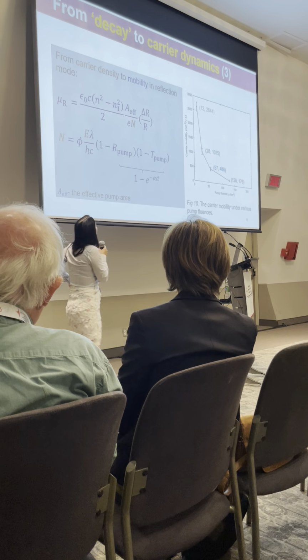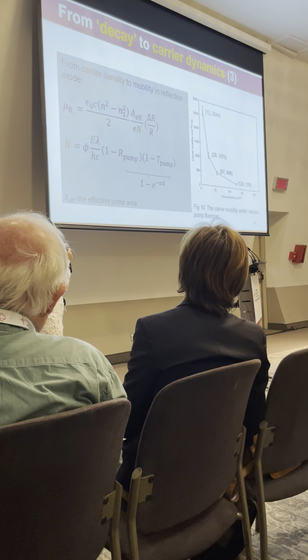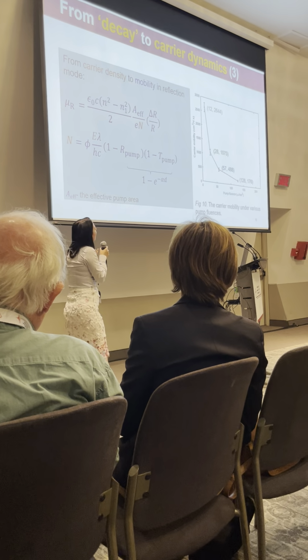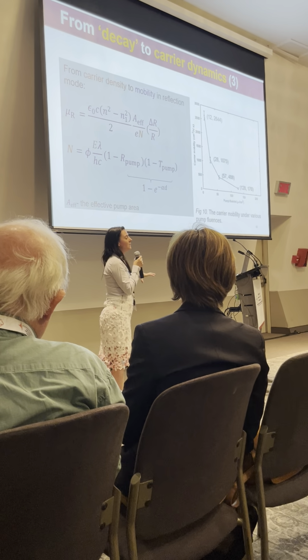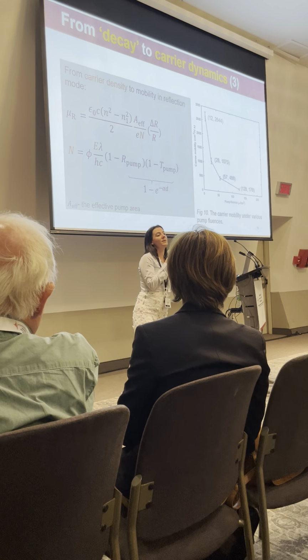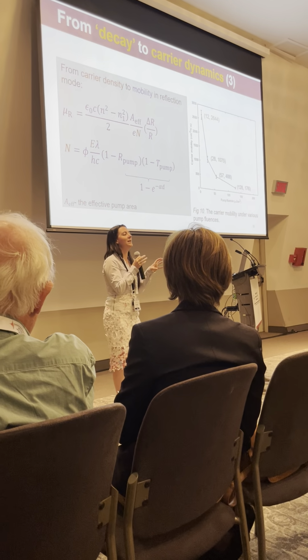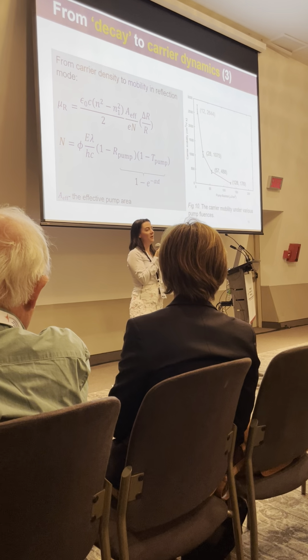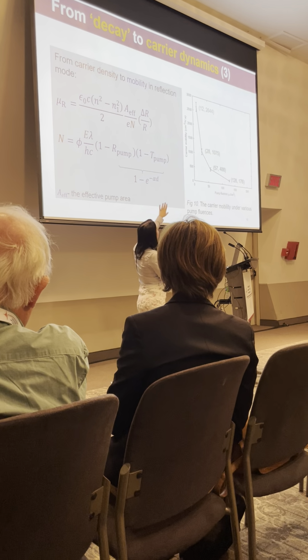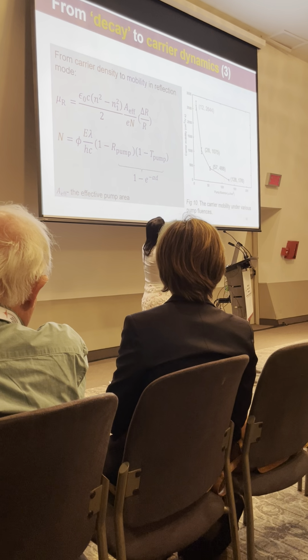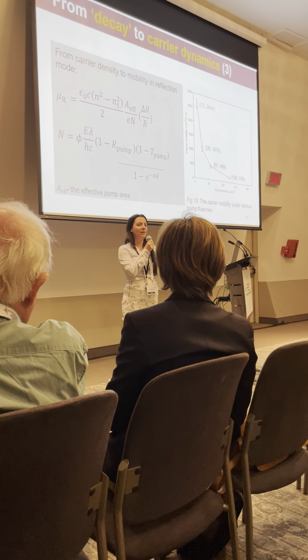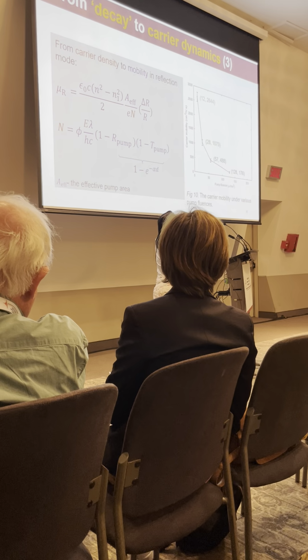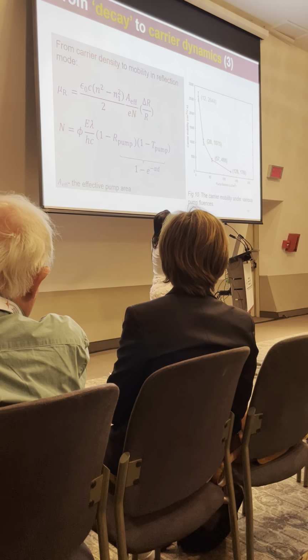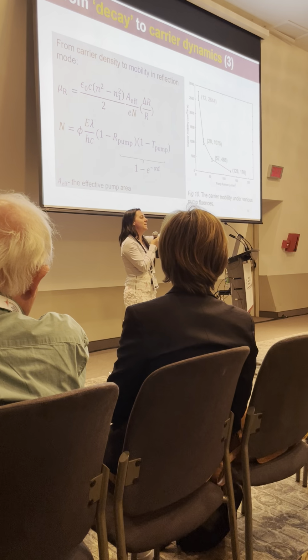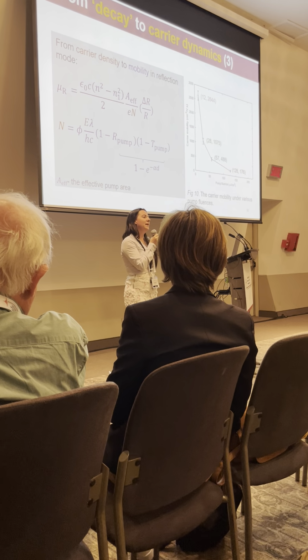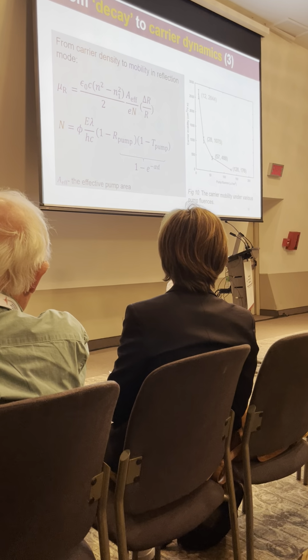We can also look at the peak of that decay and get an estimate of carrier mobility. There are some assumptions that go into this. We use the absorption coefficient, and we're also assuming that every photon generates an electron-hole pair. So this is going to be an overestimate of the mobility, but we've got some nice mobility values coming out. And we're trying to think about that solar cell operation. So we're focusing on the one where we've got the highest fluence here at the end, where we're getting mobilities on the order of about 100 centimeters squared per volt per second. And this is kind of in the range that we expect for this zinc phosphide thin film.